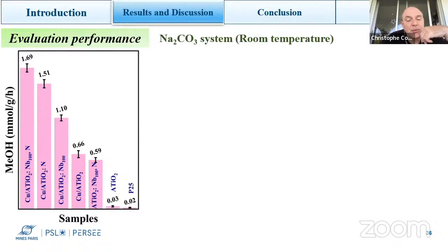Yeah, in this case you're right that you have quite the same result as with only the doped one, but I think the copper plays an important role in the reduction, not in the photocatalytic part, because you have the light absorption and creation of charge carriers happening in the titanium dioxide. But then you have some reduction step on the metal.